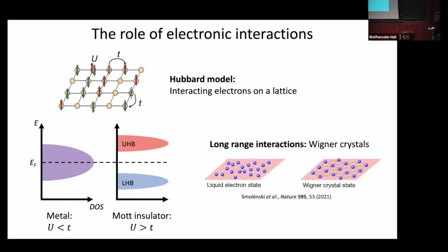You can also get similar transitions between itinerant behavior, delocalized carriers, and carriers which form some sort of periodic electron solid from long-range interactions like Coulomb interactions that you have, for example, in two-dimensional systems. If the interaction is strong enough, you go from a case where you have a liquid electronic state where, again, the carriers are delocalized. There's no translational symmetry breaking. But as you crank up these interactions, as a result of long-range repulsion between the carriers, they arrange themselves into a solid known as a Wigner crystal that minimizes the mutual Coulomb repulsion between the carriers. And so it's this kind of idea of how interactions take you from itinerancy, from liquids to solids, that I'd like to focus on in this talk.